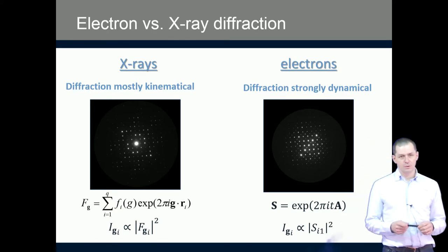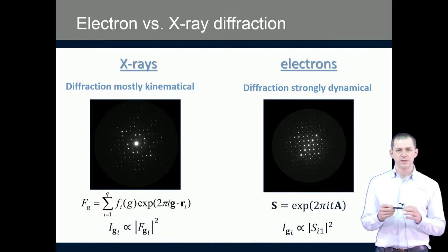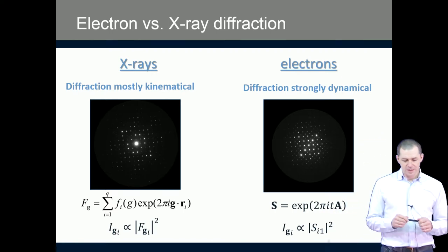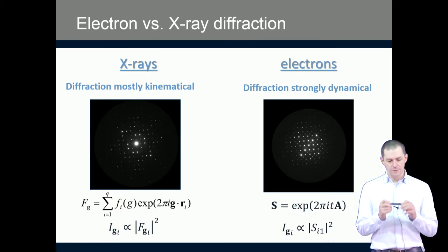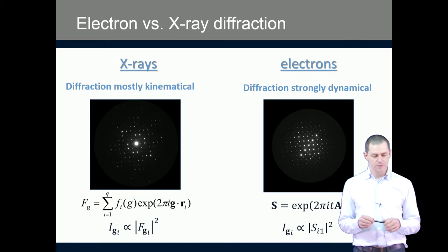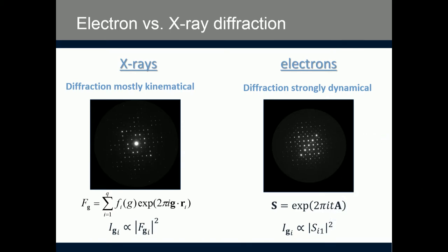Another difference that follows from the fact that electrons interact very strongly with matter is that the diffraction of X-rays can be described with the kinematical diffraction theory, which is a simplified theory of diffraction that assumes that every quantum of radiation, every photon, diffracts only once or not at all. So it diffracts at most once. If you make this assumption, then you can derive all the well-known formulas for diffraction, including the structure factor equation and the fact that the diffracted intensity in X-ray diffraction is proportional to the square of the structure factor amplitude.